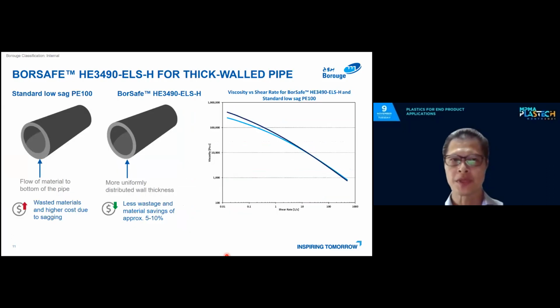Let's look at the difference between the standard low sag polyethylene 100 compared to our extra low sag material. If you look at this standard PE100, when the material exits the die after extrusion, it is still in the viscous mode, and due to gravity, the material will flow downwards, causing sagging at this bottom region, and this will contribute to wasted material and also higher costs. You have to spend time to adjust your parameters as well as the tooling just to try to get to a uniform wall thickness across the circumference.